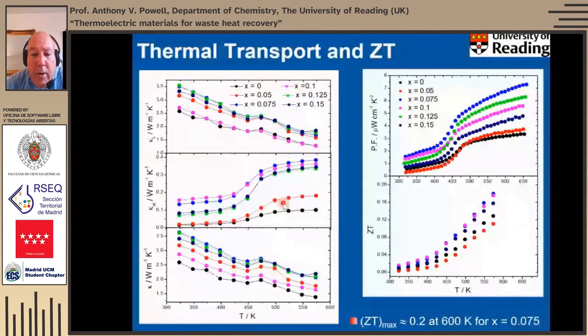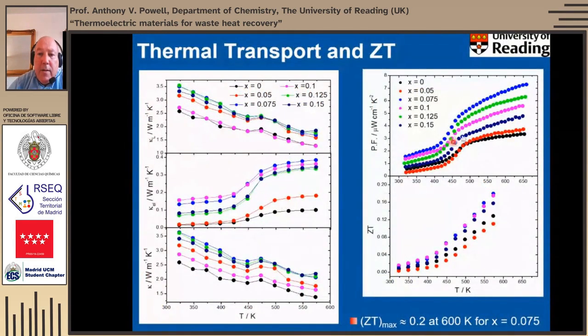So we get thermoelectric properties. I won't go through these in detail, but again, the power factors are increased as a result of those changes in the transport properties. The thermal conductivity is also increased, principally because of the changes in the electrical contribution, which are shown here. But nonetheless, this increase in the power factor is sufficient to increase the ZT slightly, and we get up to about 0.2 at 600 Kelvin.